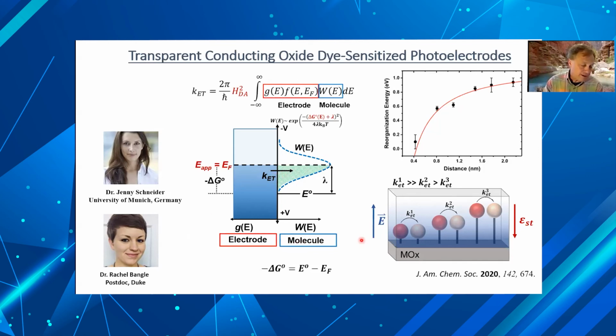And what they did was fix dye molecules at different positions within the electric double layer. And it turns out that the reorganization energy for electron transfer, which is a measure of the barrier for transfer, is directly related to the formal potential. So by measuring this whole distribution, they can extract the reorganization energy. And what they found was when they were very, very close to the surface, the reorganization energy was very small, much smaller than what we expected for dielectric continuum theory. And then when they moved the dyes further from the surface, they started getting reorganization energies that you'd expect from measurements in bulk solution.